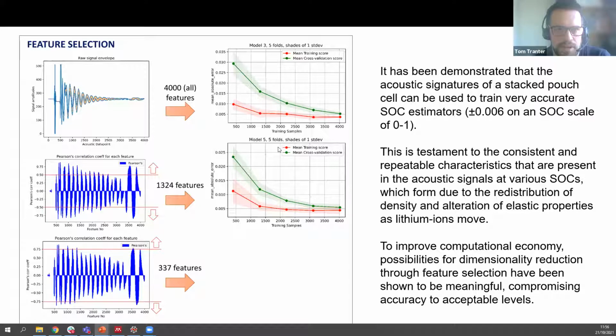And then we have a very good mean absolute error as you increase the number of training samples. So this is essentially just increasing the data set. The data set we have is reasonably large. I guess it was cycled 5 times at each state of charge, each C rate, sorry.